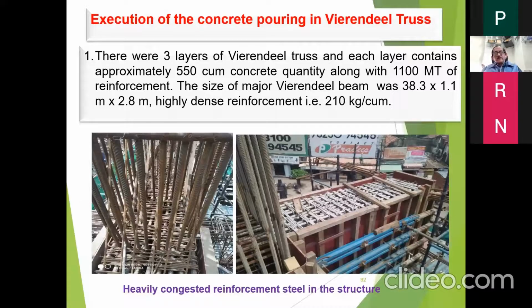There were 3 layers of Vierendeel truss, and each layer contained approximately 550 cubic meters of concrete along with 1100 MT of reinforcement. And you can see the reinforcement here. It is too congested. The size of the major Vierendeel truss was 38.5 meter with 2.8 meter depth, highly reinforced. The dense reinforcement was in the range of 210 kg per cubic meter. Normally, you know that the reinforcement in normal structures would be in the range of 80 to 120 kg. But here, due to congestion, the ratio went to 210 kg per cubic meter of concrete.